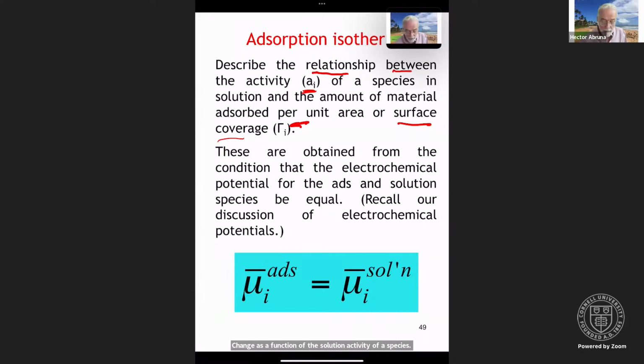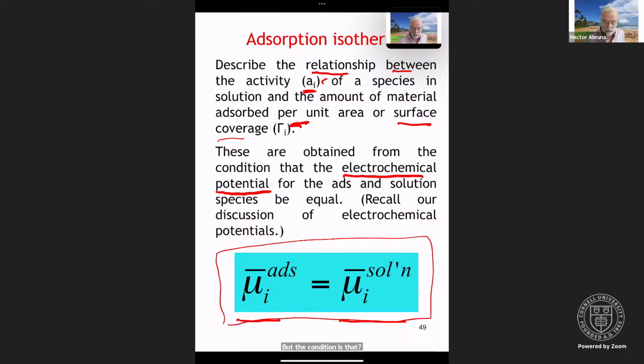How do we set up this equilibrium? Basically, we set up the condition where the electrochemical potential, I guess we didn't discuss electrochemical potential. Electrochemical potential is a chemical potential where you also include the electrostatic field, okay? And so the condition of equilibrium is that the electrochemical potential for the adsorbed species has to be equal to that of the solution species, because that defines an equilibrium condition. When you achieve that, then you have an equilibrium relationship between the solution activity and the surface coverage. But the condition is that the electrochemical potential for both the adsorbed and the solution species has to be equal and the same. If not, there will be a net transfer to achieve equilibrium.